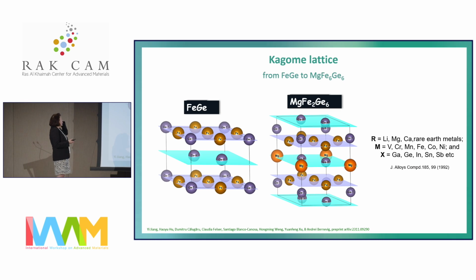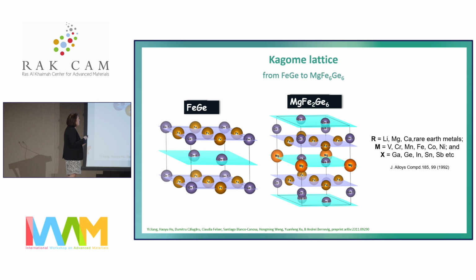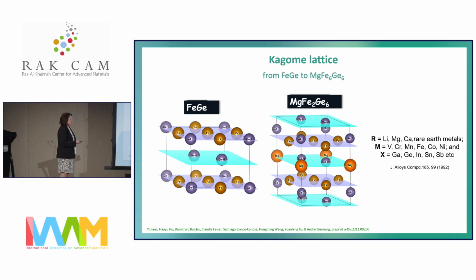So then we thought, okay, there are big groups of materials which are structurally related, for example, to iron germanium. You see the iron germanium structure, with the iron triangles, which build the Kagome lattice. So there are many other compounds which have the composition. Oh, this is a 6, sorry, this is a mistake. So it's magnesium, iron 6, germanium 6. So we simply double the unit cell and fill into some voids some magnesium. And then we can make all those compounds with vanadium, chromium, manganese, iron, cobalt, nickel, and gallium, germanium, indium, tin.